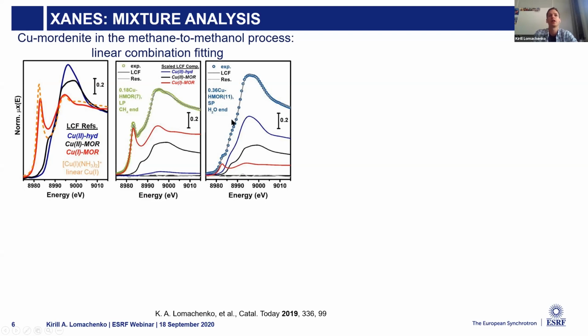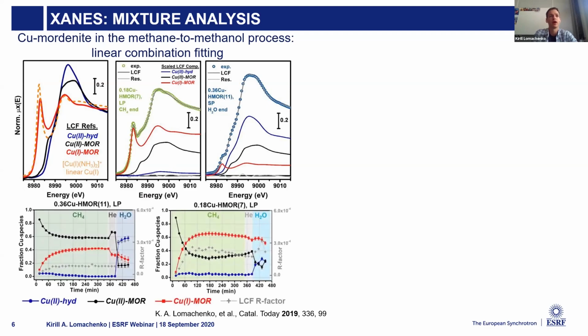You see that it works pretty well, so the agreement is quite nice if the reference compounds are selected correctly. And the good thing is that you can do this for every step of a reaction, and you can get the evolution of concentration of each particular species with time, as a function of temperature, and as a function of atmosphere, like gas composition in this case.